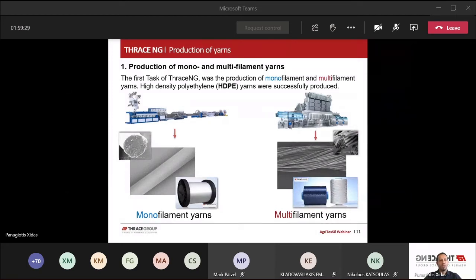Everything was just fine. Under the first task, the production of mono and multifilament yarns, it was successfully achieved using high-density polyethylene. On the left side of the slide, you can see the production machine where the monofilament yarns were produced. You can see an image here how it looks like a monofilament yarn and the cross-section of this yarn and how is the final commercial product. On the right side, you can see also the machine producing the multifilament yarns. Multifilament yarns are actually several monofilament yarns of smaller dimensions, smaller diameter, twisted together into forming a bundle. And below you can see also the commercial product, how it looks like.